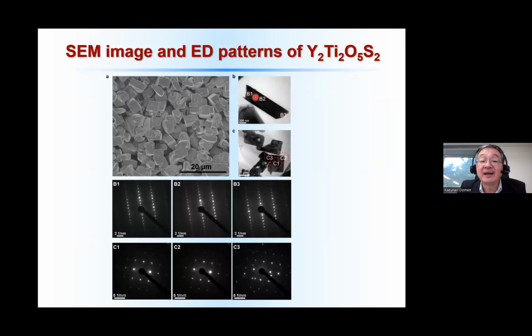However, when we took the electron diffraction pattern from different positions of one particle, like this one, it shows almost the same diffraction pattern. So these particles seem to be almost single crystal particles.